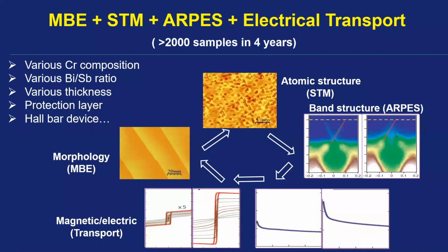So next, that's the first year's work, and in the following years, I grew almost 2,000 samples and systematically changed the chromium doping, also changed the bismuth antimony ratio to tune the periodicity of the sample, and we changed the thickness of the sample. Also, you know that the MBE-grown sample is very sensitive if you take ex situ transport measurements. You need to put on some protection layer. So we also tried different protection layers and different configurations of the Hall bar device. And we used this loop to improve the figure of merit for the magnetic doped TI.